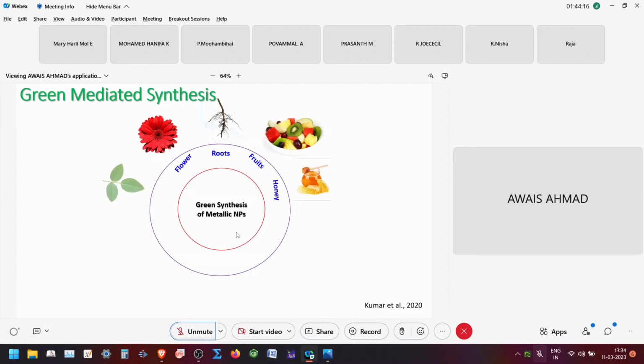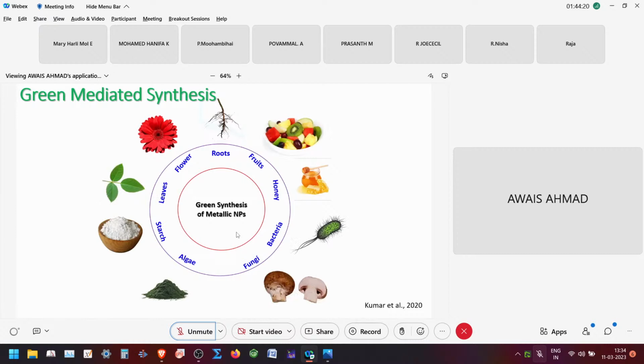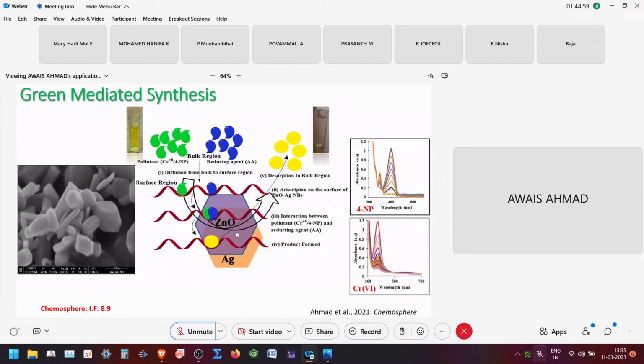Here, what we did, as you know, we take guava seeds, make the powder, and treat it with silver nitrate, and at the end we get silver nanowires, which we use for the degradation of methylene blue. Same here, we take a Texas sage plant and its extract, and then we use it for the degradation of methylene blue. And same here, we take zinc oxide, silver, and add the ascorbic acid treatment, and then we use this for degradation of 4-nitrophenol to aminophenol and chromium 6 to chromium 3. And here you can see the shapes that we get: nanoprisms or nanobars.